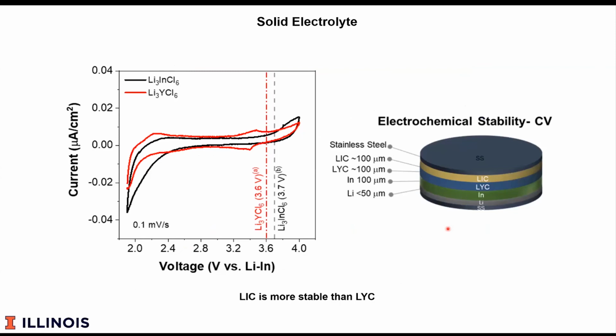We're using these halide salts. These are an area of recent interest. They have high voltage stability, and so they're stable. Particularly the indium-based one is stable against lithium cobalt oxide. There are other variants we're exploring. This is the details of the cell design. Feel free to ask more questions later. As a detail, we use indium because these are not stable at lithium, so there's a current challenge. But these are soft enough that they can be physically pressed to interface with solid electrolyte.